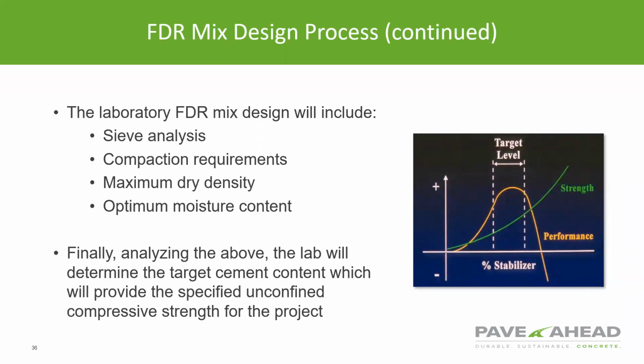Typically, we will see those unconfined compressive strengths in the range of 300 to 400 PSI. And one point I want to make is that more cement is not necessarily better. So keep that in mind. We're looking for a balanced design. And when I mention balance, we really want to be in this target level, right in this area.